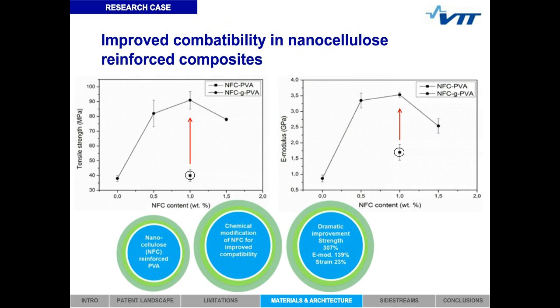The last example highlights the importance of compatibility. In this example, we used nanocellulose mixed with polyvinyl alcohol. Polyvinyl alcohol is highly hydrophilic, as is nanocellulose. However, the compatibility is still far from optimum. So in this case, we modified nanocellulose with an epoxide group so that we were able to form a covalent cross-linking with the PVA matrix.